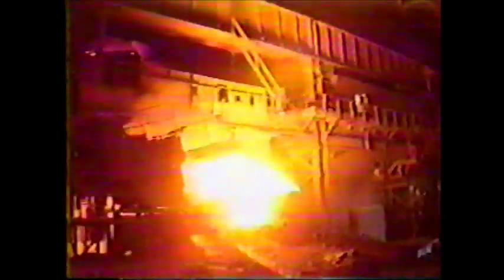Warren's 2-vessel basic oxygen furnace replaced 8 250-ton open hearth and 2 250-ton electric furnaces. The BOF produces steel with carbon contents from 0.015% to 0.85% at the rate of 140,000 tons per month. Warren specializes in electrical steels, high carbon or low alloy steel, each of which may be supplied with ultra-low sulfur and very high internal quality.